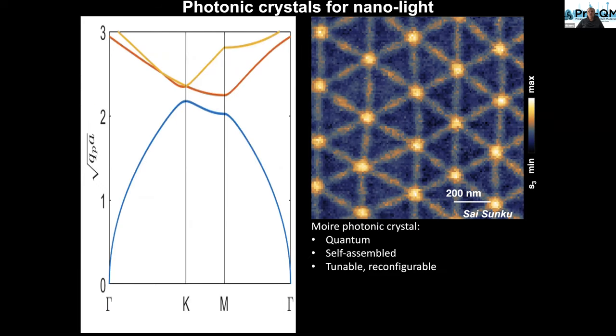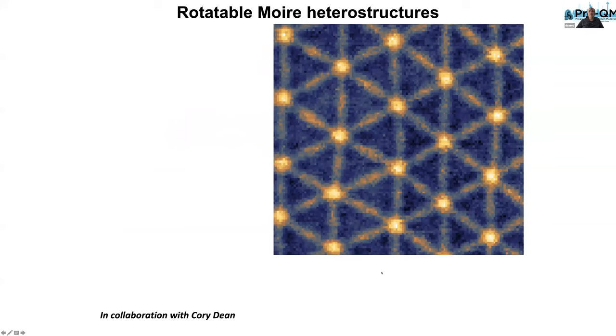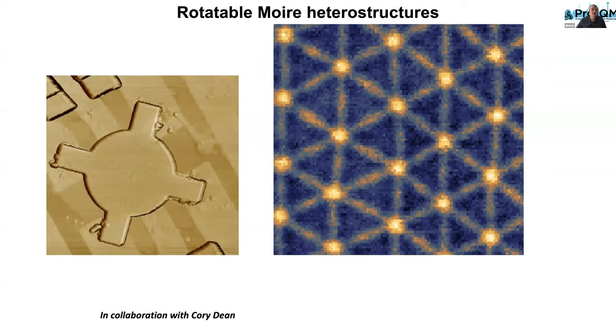So this medium is continuous. We are not drilling any holes in this medium. This medium is continuous, and reflections of a plasmonic wave happen because of a quantum effect, because of reconstruction of the electronic structure at the domain wall. These objects are self-assembled. You don't need to drill any holes here. What you need to do is to rotate one layer with respect to the other, and then you get this network, a network with variable period also. So these are also tunable and reconfigurable photonic crystals.